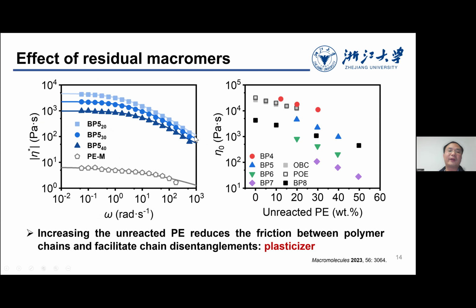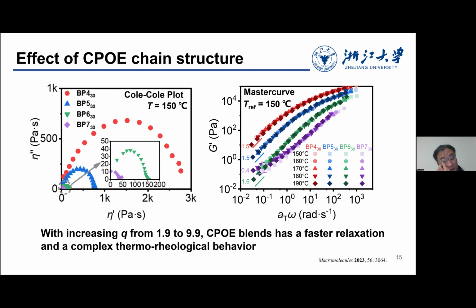And we further studied the effect of the residual macromonomers on the polymer processing. What we have done in this work is we mixed some macromonomers with the copolymers we synthesized and tried to find the rule: when we increase the unreacted macromonomers inside the system, how it will change the rheology properties of our copolymer system. And we found the unreacted PE residues actually play a role of plasticizer during the process, so that they can reduce the friction between the polymer chains and facilitate the chain disentanglement of these CPOE polymers.